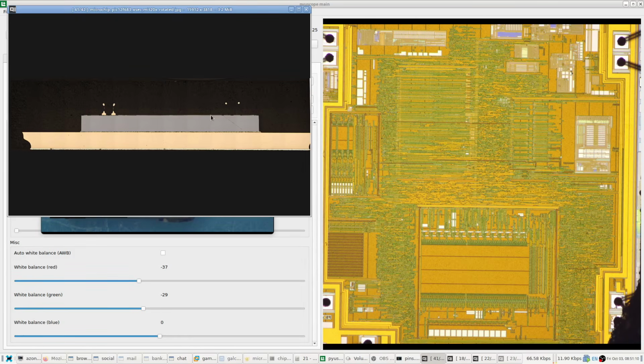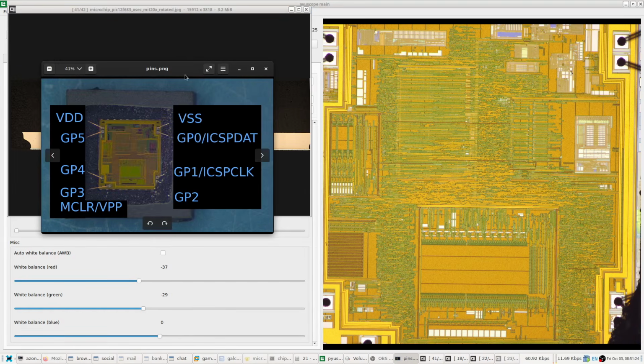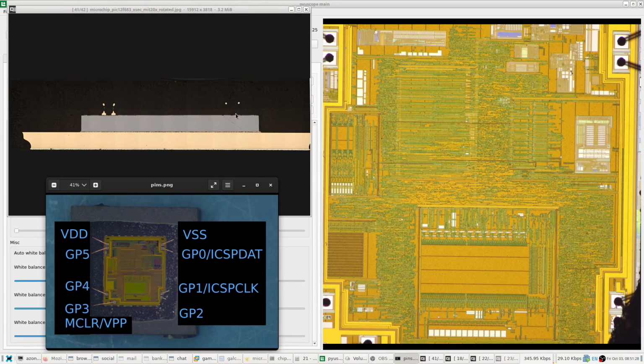Also, while we're still looking at the 5x overview, just to get you oriented as far as the various images we're looking at, this is the cross-section that we took in the first part of the video. And so we are looking in now from the right side of the image. And so this bond wire right here, which is the VSS bond here, that is this wire here. Then we've got GP0 here and here, GP1 here, and GP2 here and here. And so we're looking in essentially this whole side with the sectioning plane tilted slightly to the right of vertical. So we're dead center in these bonds, and then dead center in these bonds, and then just slightly inboard. So we're at maybe a degree or two counterclockwise of perfectly vertical in the cross-section plane.